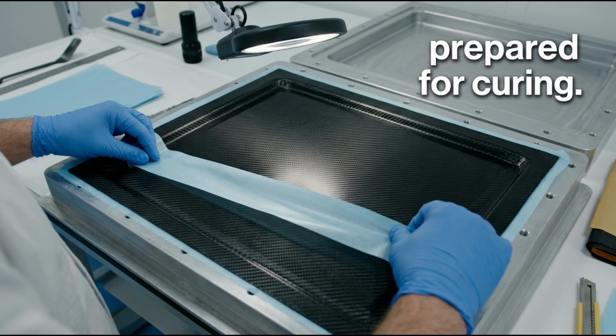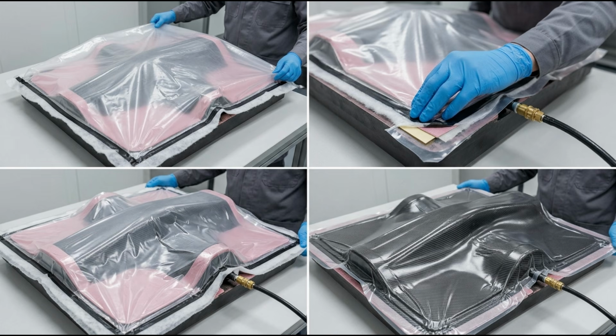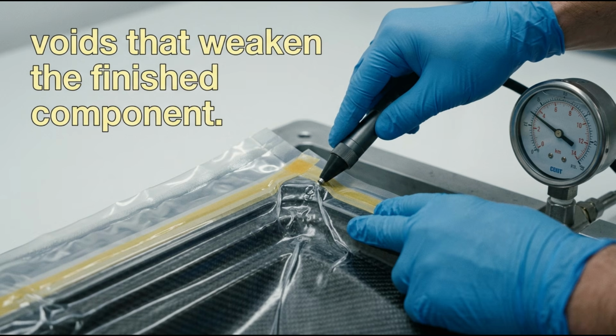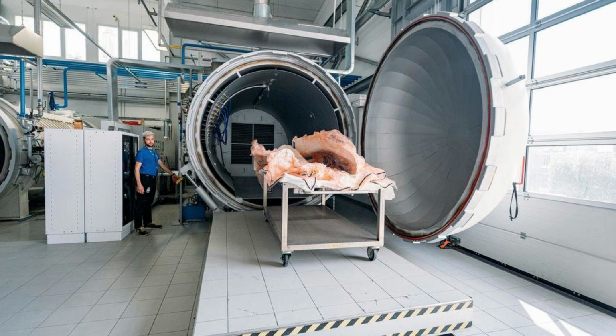Vacuum draws air from inside the bag and compresses the material against the mold. Technicians check for leaks. A poor seal could leave air inside the laminate, creating voids that weaken the finished component. The bagged mold enters an autoclave, a large pressure vessel that applies a controlled combination of heat, pressure, and time.